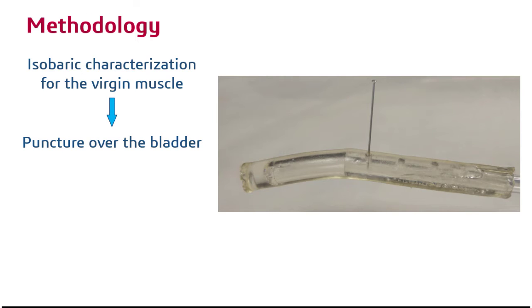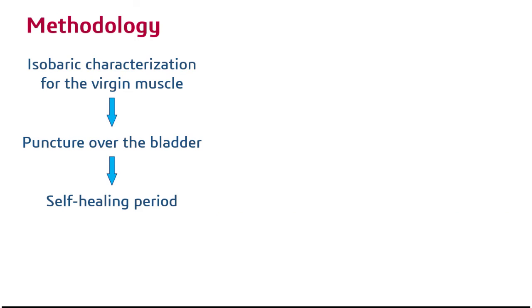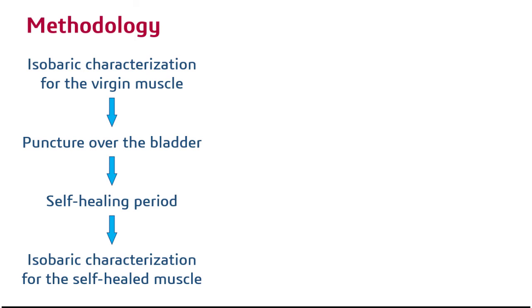This system is responsible for providing the muscle with gas from the network. Having the hydrogel-based muscle and the stub, now we want to characterize these muscles and to prove the self-healing on them. So we established this methodology. First, the typical isobaric characterization for the virgin muscle is obtained. Then, the bladder is punctured and is left under ambient conditions during a specific time in which the self-healing process takes place. In this case, we consider 3 periods of time: 10 minutes, 2 hours, and 1 day. After that, a new isobaric characterization for the self-healed muscle is obtained.